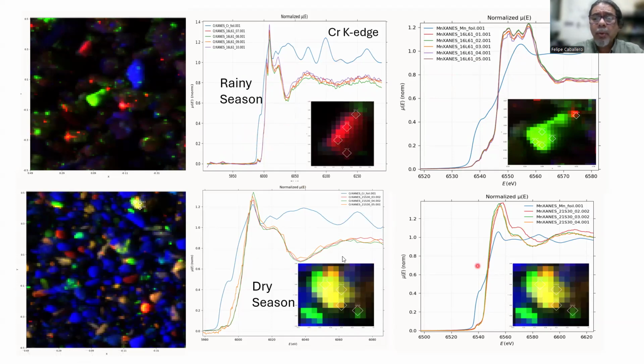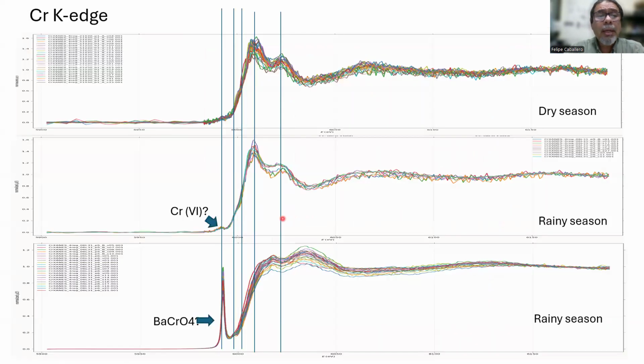In the case of the rainy season particle, also for the chromium edge, we performed these spots. We get spectra, and for manganese, you can see from here that there are differences between manganese in the rainy and the dry season, and chromium in the rainy and the dry season. So we have different species, but to have more statistics, we select several particles in each of the samples. We map different regions of the sample to have more statistics and be able to draw more conclusions.